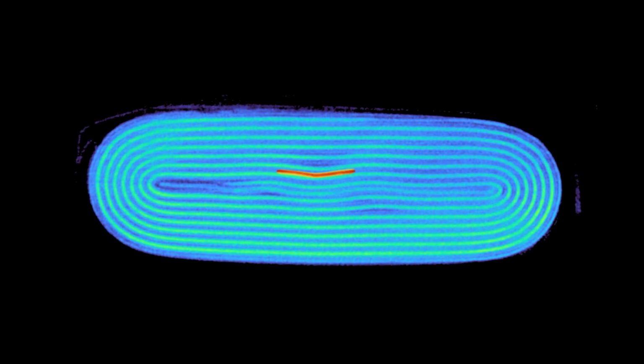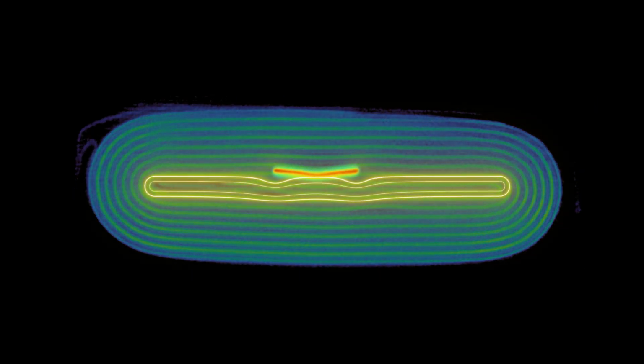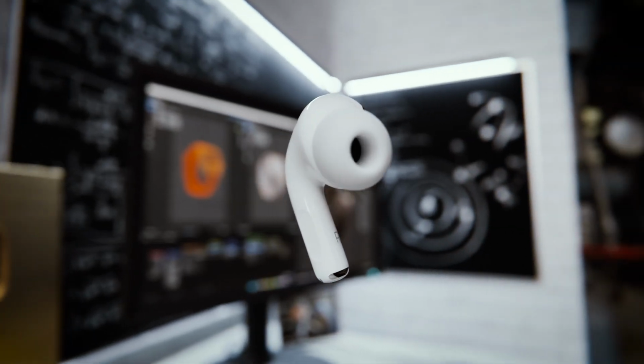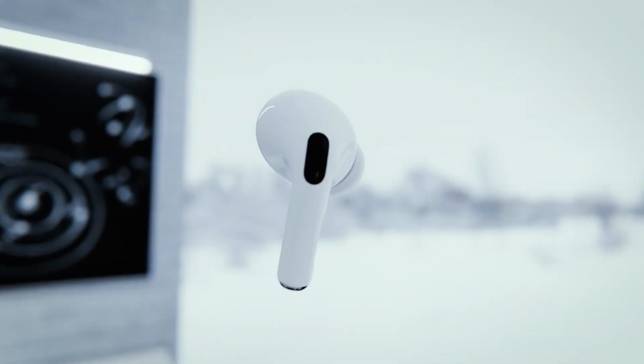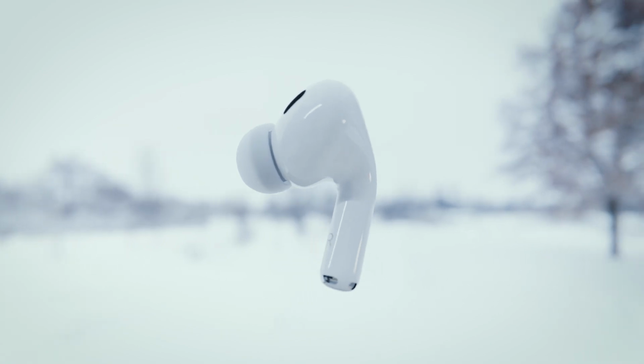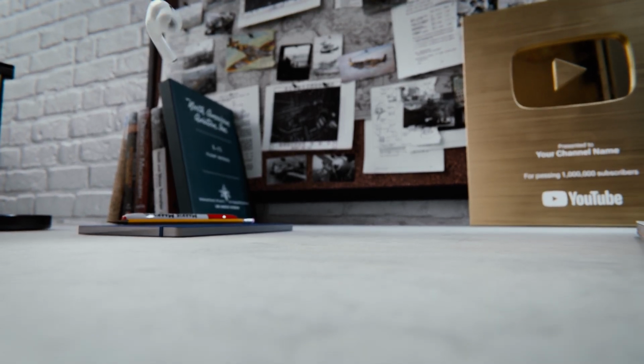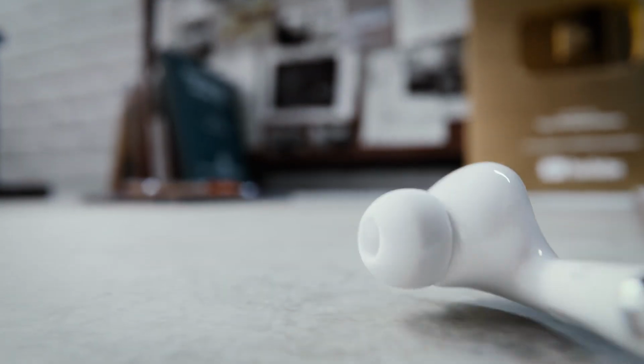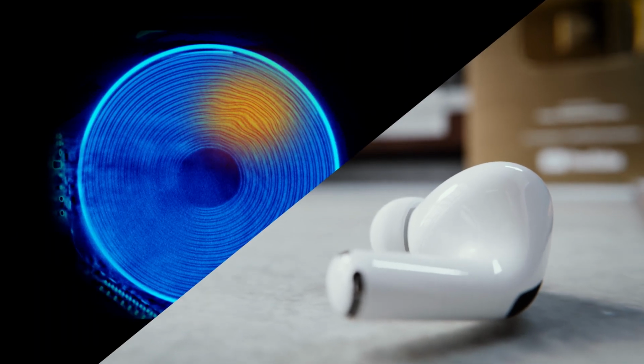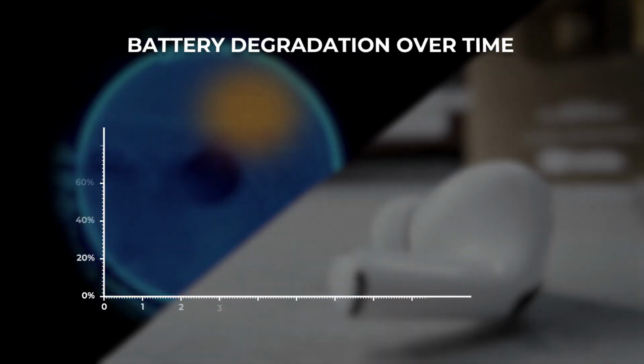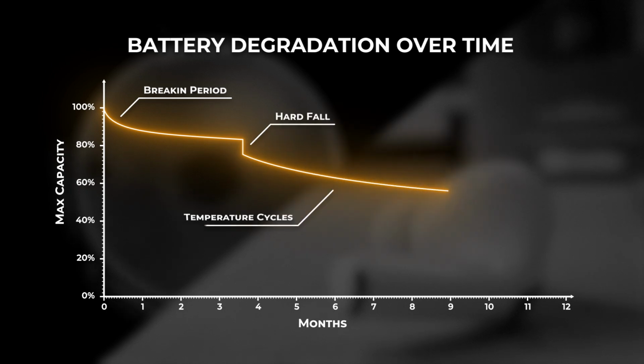Here in the scan of the charging case, there is a faded patch in the corner. That is where the electrolyte has broken down. It is no longer making contact with the electrodes, so ions cannot move through that region. This is literally a dead zone in the battery. These zones can form when you move your AirPods from a warm room to the cold outdoors, or if you accidentally drop them on the pavement. These sudden changes in temperature or physical shocks can stress the battery's internal layers and start breaking them down. And it's one of the reasons your AirPods might start out with 6 hours of battery life, but after a year, the battery life decreases to only 2 or 3.